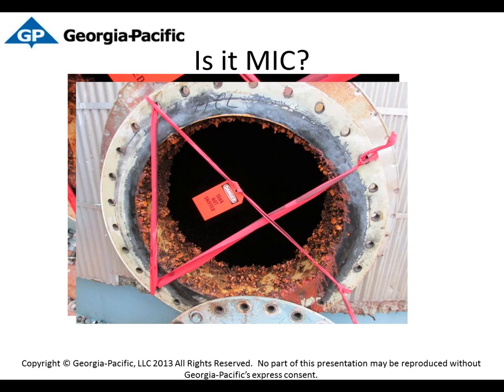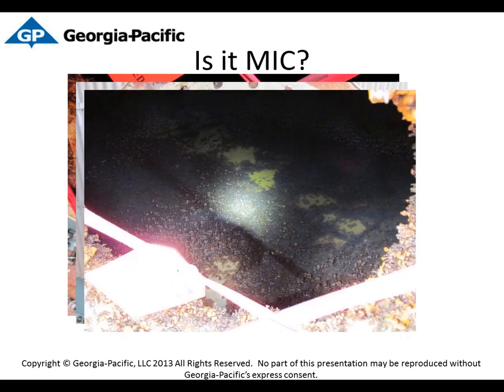But as you can see from some of these pictures, this tank was just completely covered in tubercles from the floor to the ceiling. Again, this is just hot water. This is 150-degree hot water. And when we actually did the inspection of this tank, these tubercles over the past 5 or 6 years have actually made quarter-inch pits on this half-inch thick plate wall. So we've gone through about half the tank life, a matter of about 6 years, due to the tubercles growing on the wall.